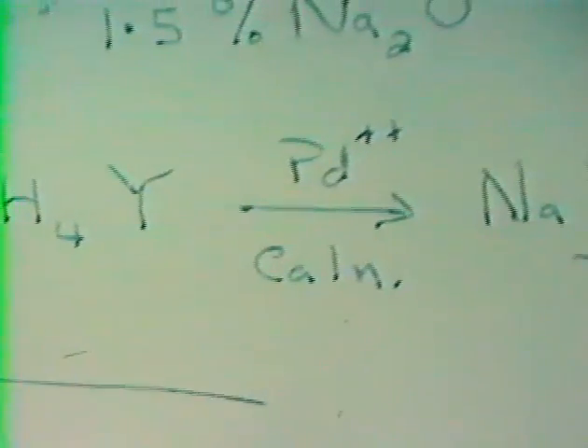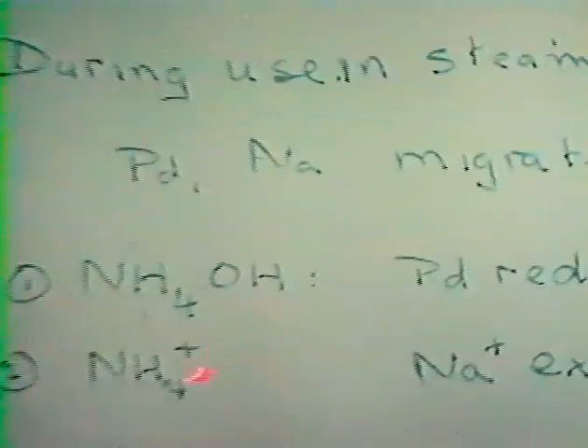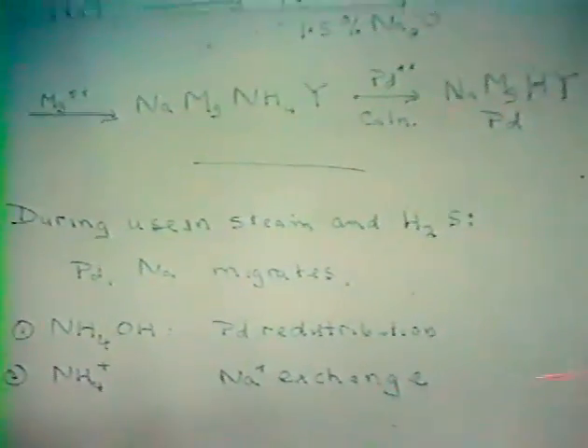What happens during use in a commercial unit is that in the presence of steam and hydrogen sulfide, both the palladium and the sodium migrate. The sodium ions migrate into the super cages, where they damage the catalyst acidity and therefore its cracking activity. We can restore that activity simply by ammonium ion exchanging the sodium out. Similarly, the palladium has migrated, and we can restore that activity by treating with ammonium hydroxide, which reforms palladium tetramine solution, which then re-exchanges into the zeolite at ion exchange positions.